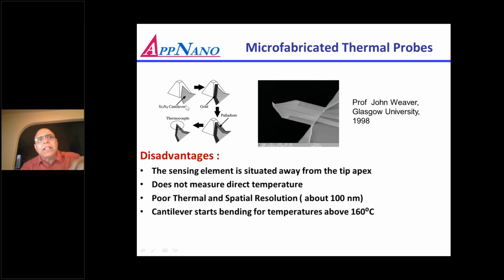As the scan keeps continuing, the nitride cantilever wears out, and so your thermocouple is coming closer and closer. That changes any calibration you might have done before starting the experiment, because the distance from the sample to the sensor is changing. So this is another drawback here.